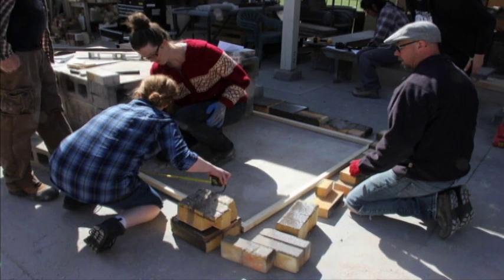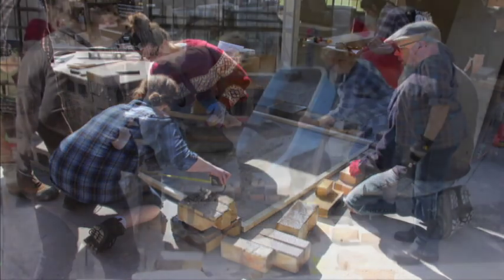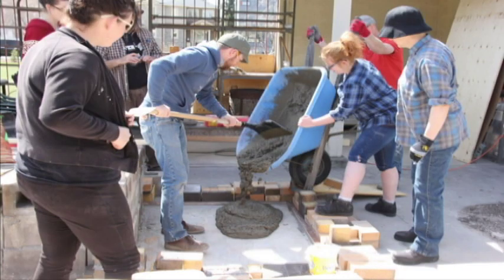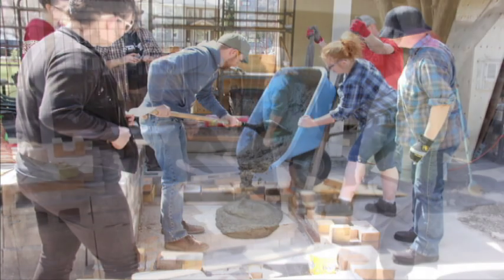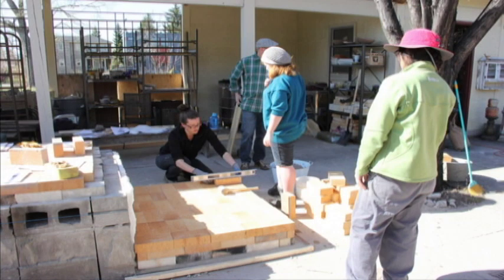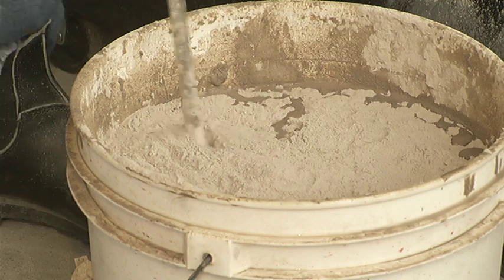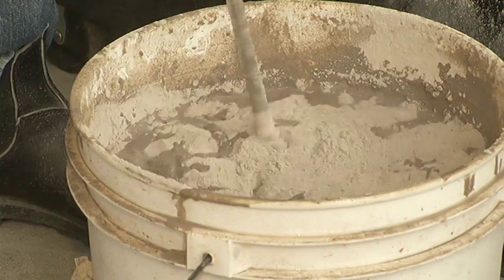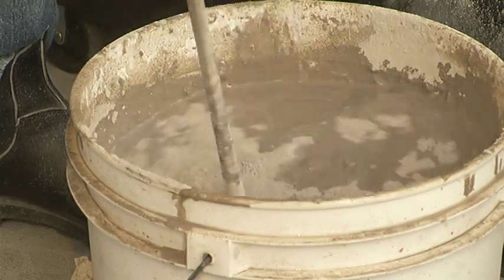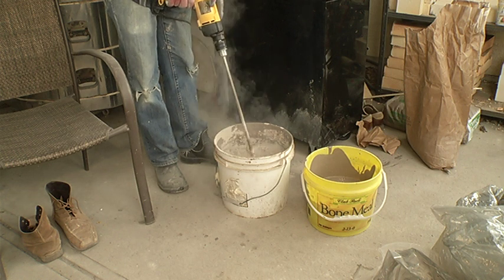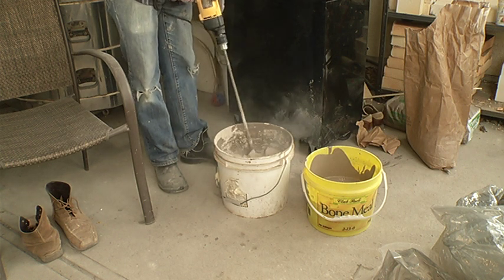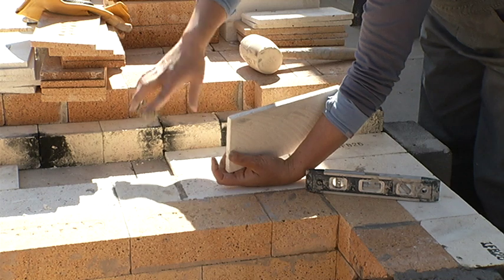We decided all we could salvage was the cinder block base of the arch and chimney of the old kiln. We poured a new base for the firebox. Because the kiln is a dynamic structure that moves as it heats and cools, we can only use traditional bricklaying techniques in a very few places. Instead, we use a clay slurry to plug the irregularities between the bricks and create a gas seal that increases the heat retention of the kiln while allowing the structure to move.